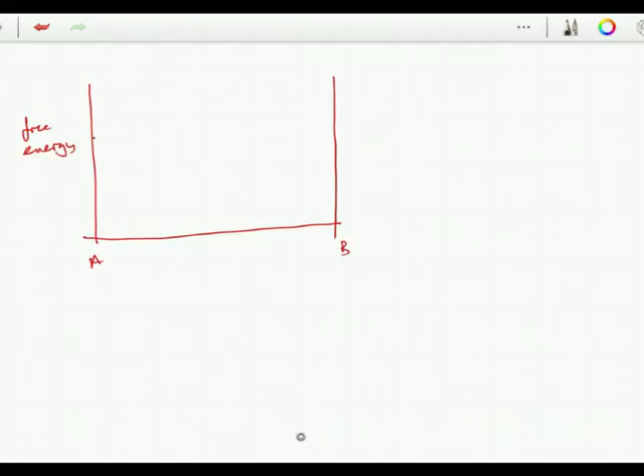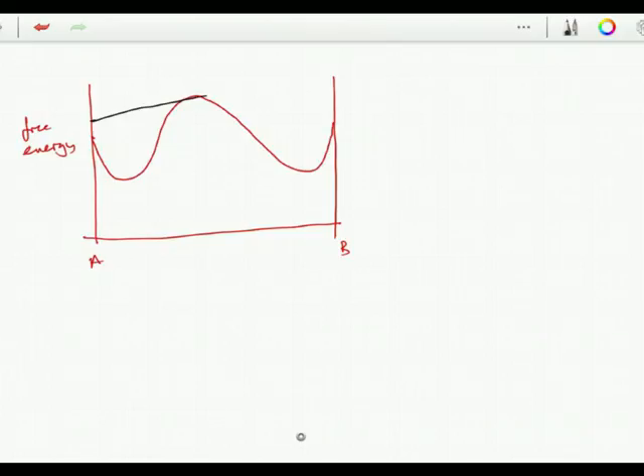In contrast, if my free energy curve looks something like this, so that there are minima at low concentrations of B and at high concentrations of B, which means that like atoms prefer to be next to each other. So this is an A-rich solution and this is a B-rich solution. On this particular plot, if I draw a tangent to the curve at this point, so that's my concentration C1, and that will be mu B at the concentration C1. And for another higher concentration, mu B of C2,